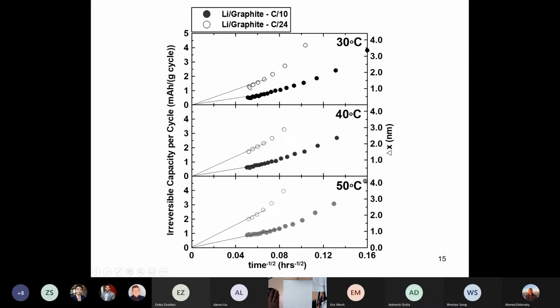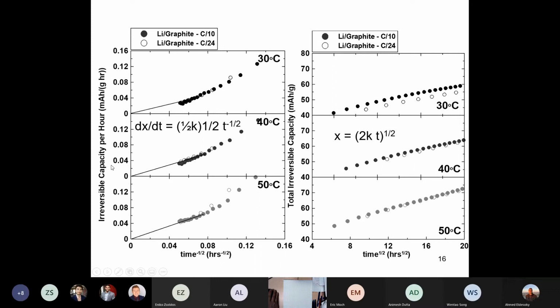So anyway, the point is, if Aaron's right, and it's all about time, if we plot the irreversible capacity per unit time, these two data sets should lie right on top of each other. And so that's what we do. We plot the irreversible capacity per unit time per hour. And sure enough, the C over 24 and the C over 10 data lie exactly on top of each other. So this was the first time that anybody had ever done an experiment like this. And it's a hard experiment to do unless you have an ultra high precision charger to really look carefully at this.